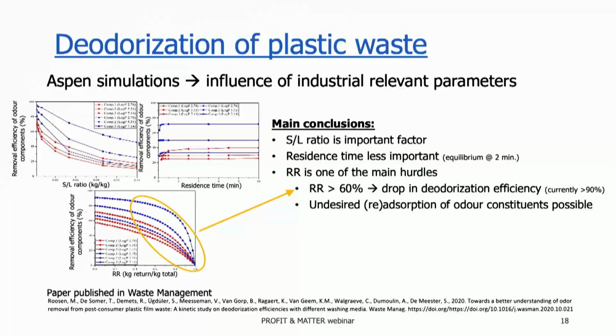As a next step, we performed some Aspen simulations to investigate a bit more in depth some industrially relevant parameters, such as solid-liquid ratio, residence time, and recirculation rate. What we saw is that the solid-liquid ratio was quite an important factor, since the higher the solid-liquid ratio, the lower the efficiency obtained. On the other hand, the residence time is not very important, because what we saw is that an equilibrium was already achieved after 2 minutes.